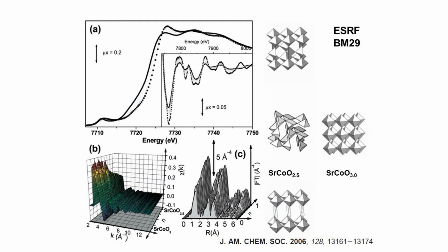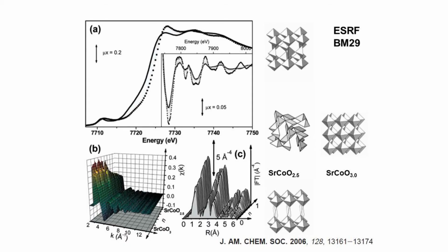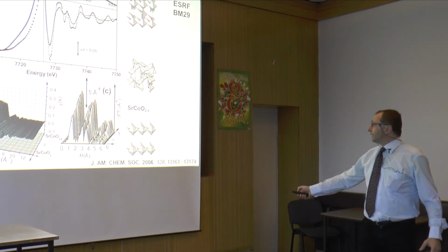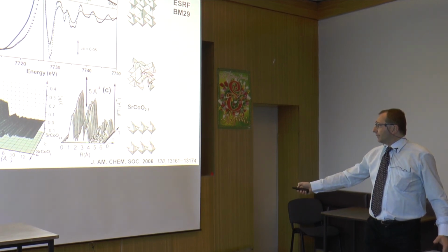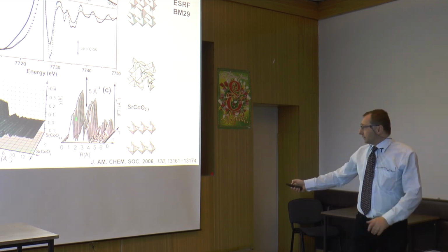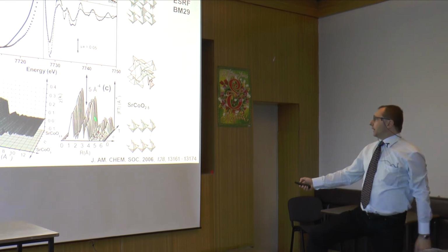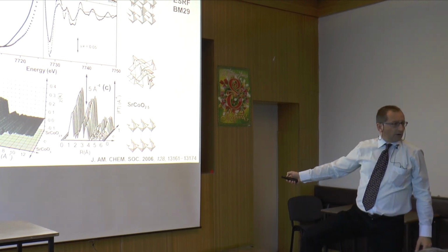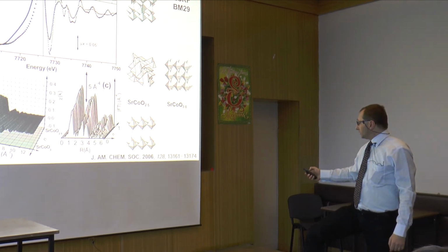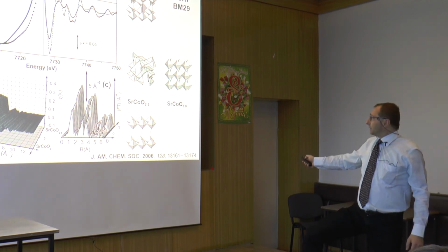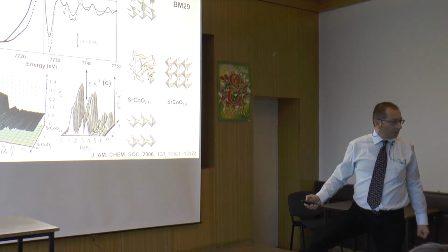This is perfectly understandable because we are moving from a sample that in the first shell has tetrahedral and octahedral to a phase that has only octahedral. So the number of oxygen neighbors on average increases. But what is impressive is how the system becomes more structured and more ordered in the long-range region. You see that here we have noise. So in the starting phase we have signal up to more or less 4 Angstrom if we take into account the phase correction, while here we start having important signal even at much higher distance. This is because the final system is very ordered and multiple scattering contributions are dominant in this case.